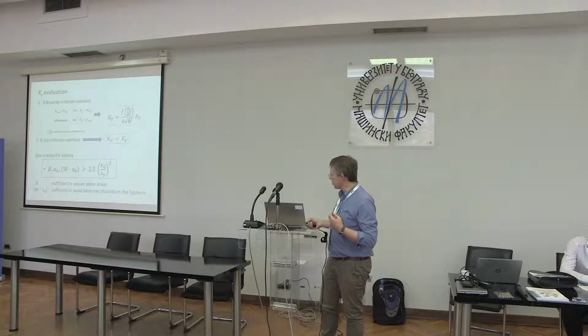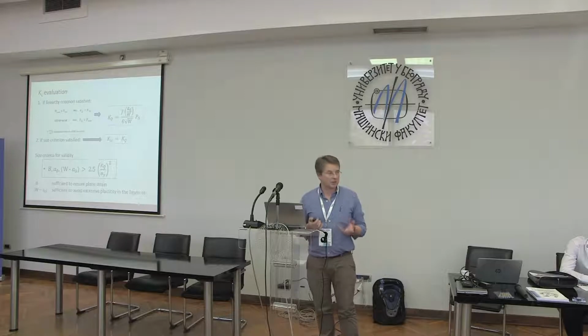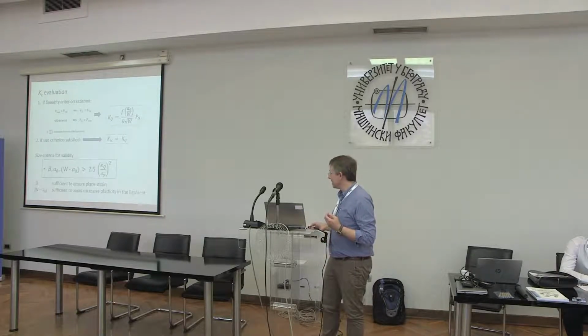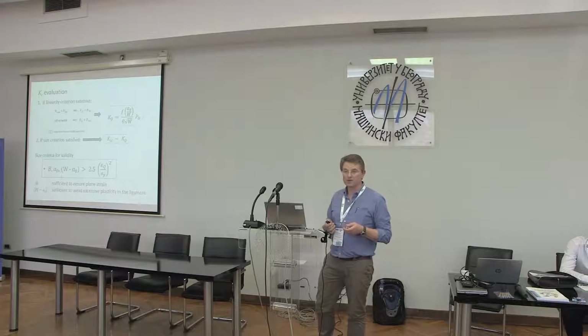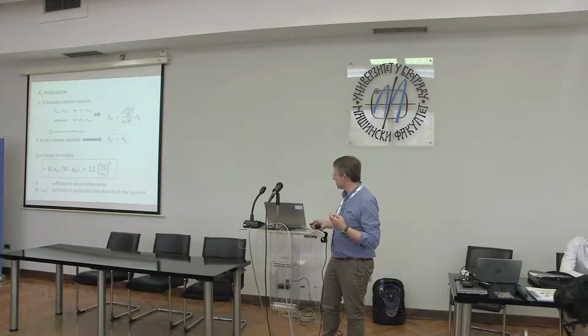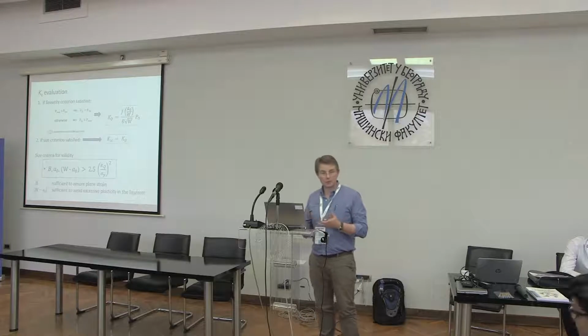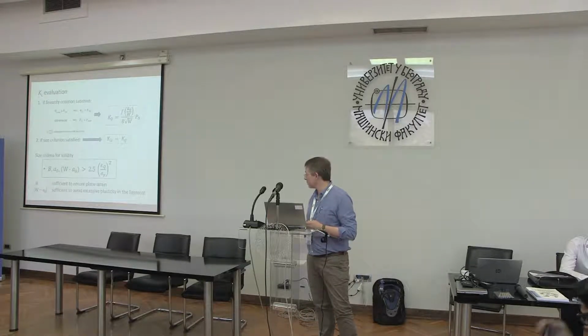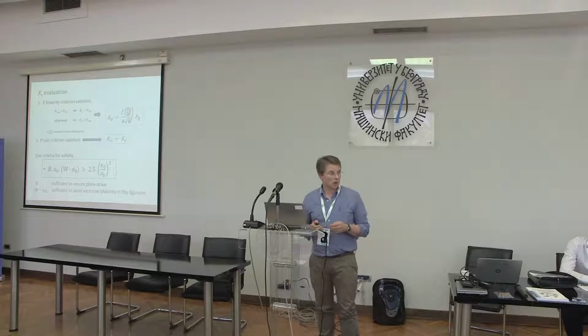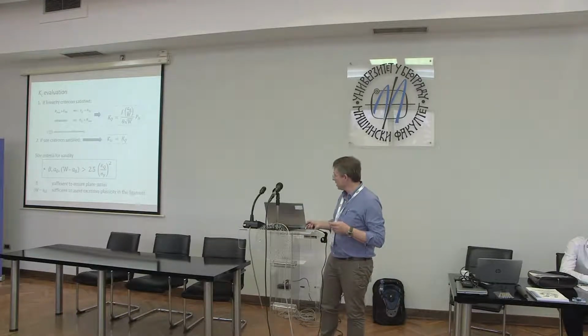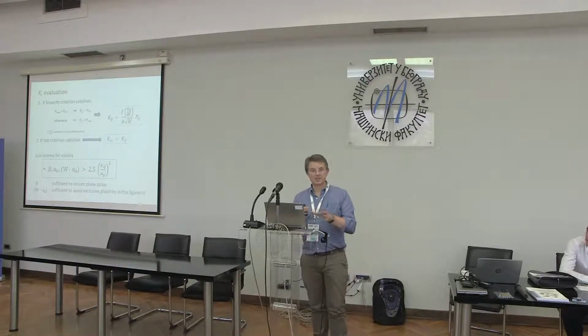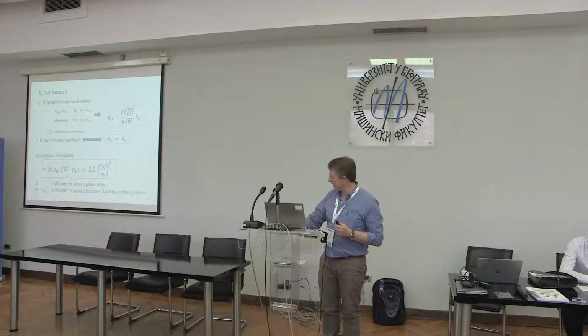What are the size criteria? Well, of course, we have to check that our critical dimensions in the specimen, a, B, and the ligament length, W minus a, all are greater than 2.5 times (provisional KQ over sigma Y) all squared. So we check that, that's the size requirement. If that's satisfied, this ensures the plane strain condition, and this condition here ensures that we avoid excessive plasticity in the ligament of the specimen. So that's our standard approach for K.